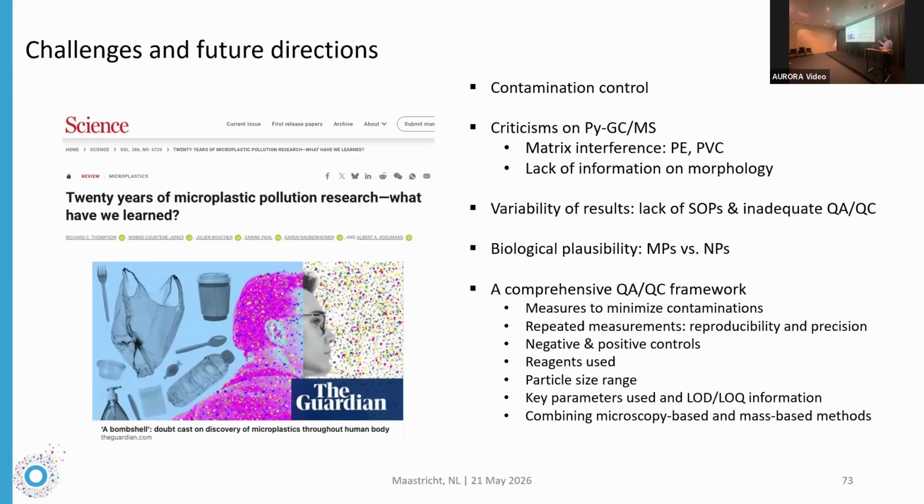And also the particle size range, because it can be subject to many factors, including the method we use, but also the digestion and the filtration process. And also the key parameters used, for example, for pyrolysis, we need to make note of which reference material we use and which calibration standard we use. Also the LOQ and LOD information are crucial. And it is also recommended to combine microscopy-based methods and mass-based methods in the same study to complement the results of each other.